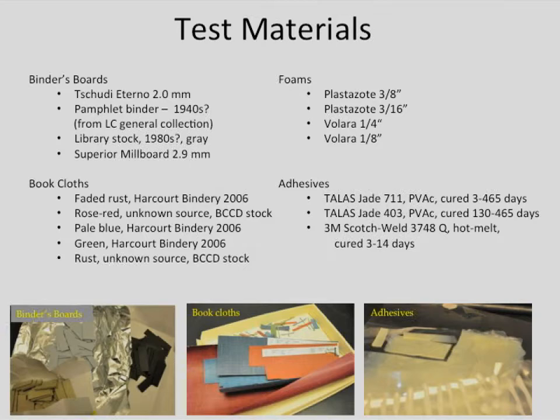For the Oddy test, we would just chop the samples up into small pieces. That's easy to do with these binding boards and book cloths. For the adhesives, we would use Mylar and spread a thin film of the adhesive out and cure it for a certain amount of time, then try to peel it off the Mylar. For those that didn't peel off, we would scrape them off, using in each case about 2 grams of material.